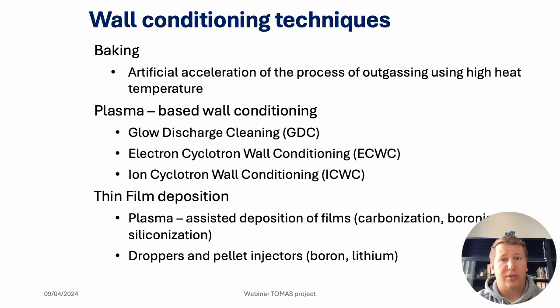The second type is based on the particle-induced desorption mechanism. We use auxiliary plasmas to create a particle flux to the wall, which stimulates the removal of the trapped impurities of UL species. Different types of plasma discharges are employed depending on device conditions.